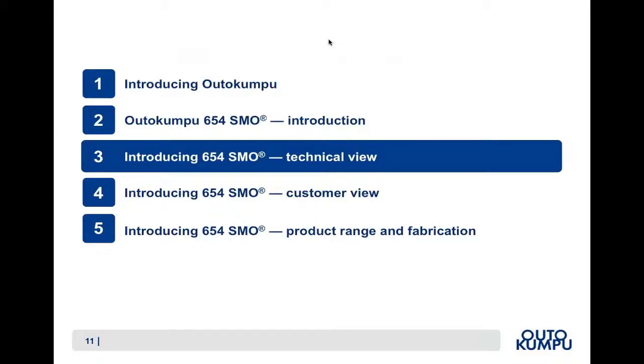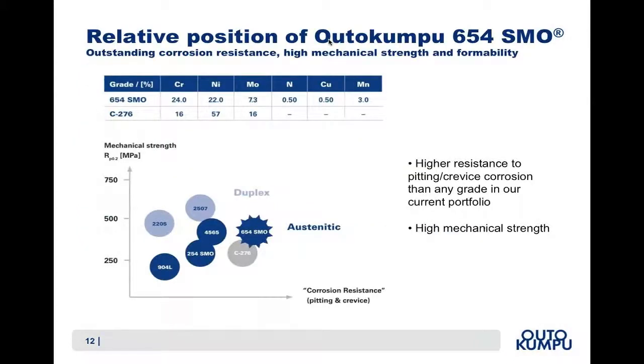Now let's take a look at some more technical information about 654 SMO. Looking at the relative position of this grade compared with other stainless steels and nickel-based alloys. If you look at the chart, which plots the mechanical strength and corrosion resistance, you can see that 654 SMO falls to the right of all the other grades here, and also higher than the nickel-based alloy C276. Also, if we look back to the vertical axis, mechanical strength, we can see that 654 SMO is again superior to the nickel-based alloy C276.